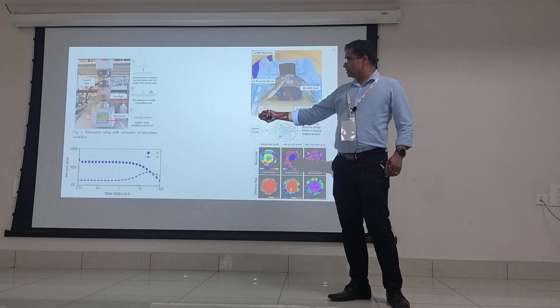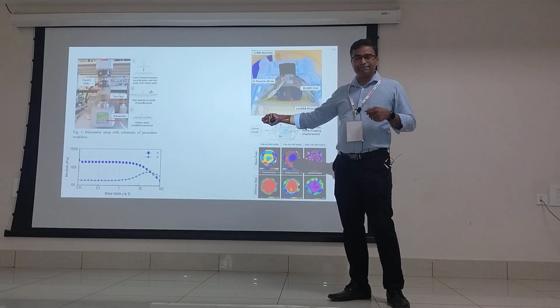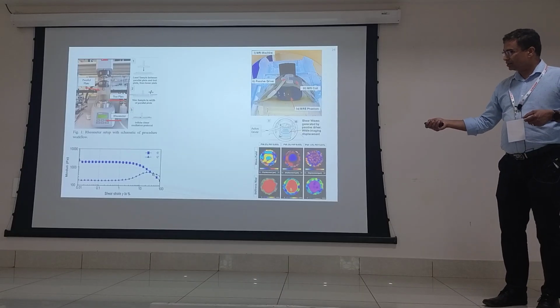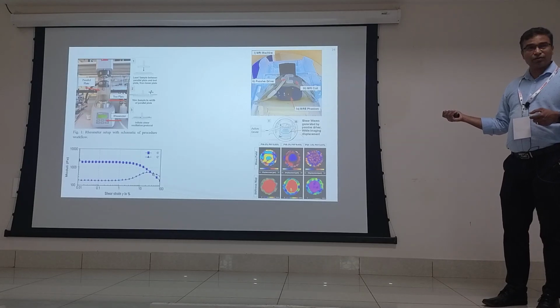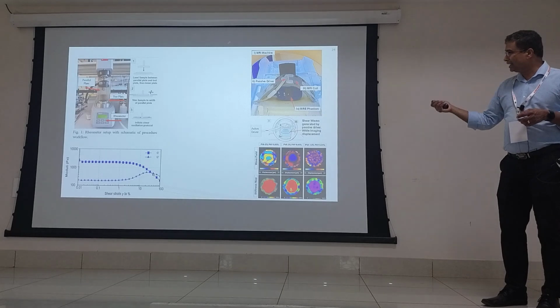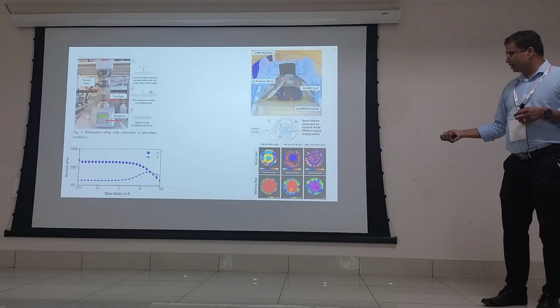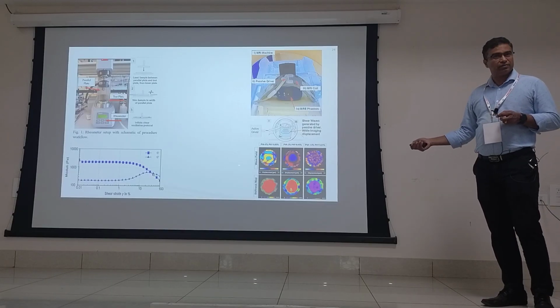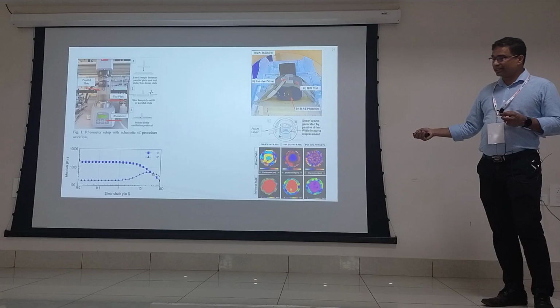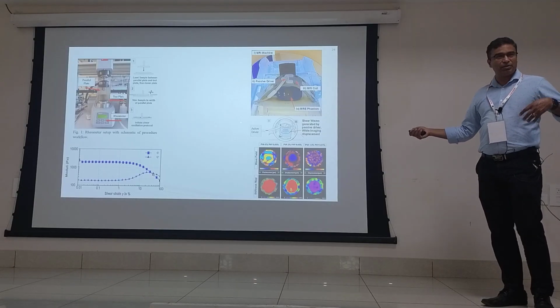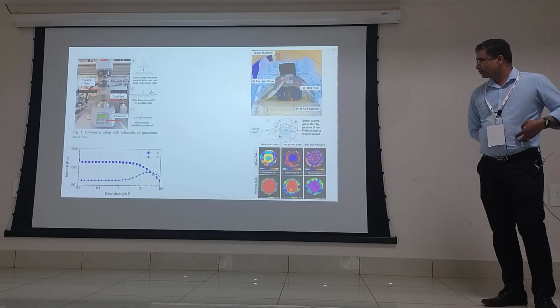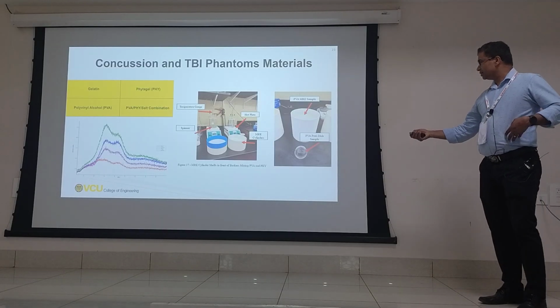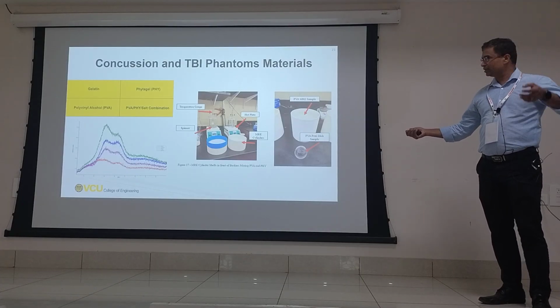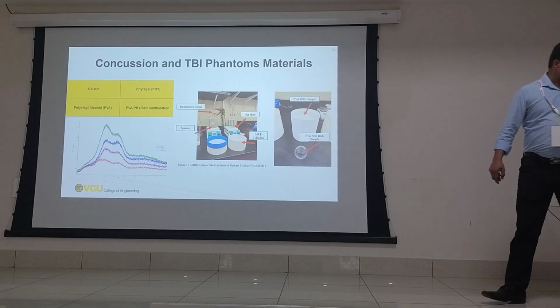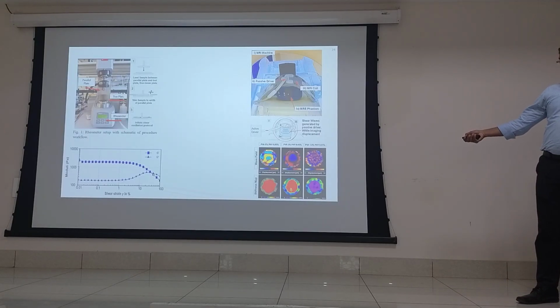So without contact, rather than applying a shear stress and calculating the shear modulus or loss tangent, you can use a sonograph or an ultrasound transducer in an MRI to get the elastic constant of the material. Okay, so that's a new technique, but it exists. It can be done for liver, and it's shape dependent. So we basically made a standard sample, without mimicking liver or brain, wherein we can get the stiffness constant from MRI.